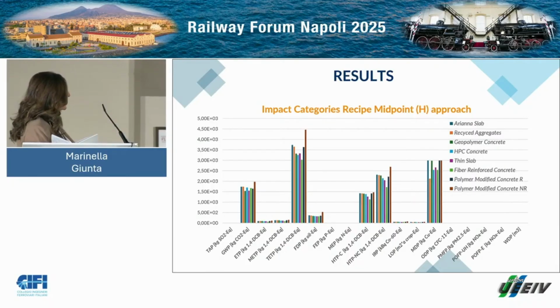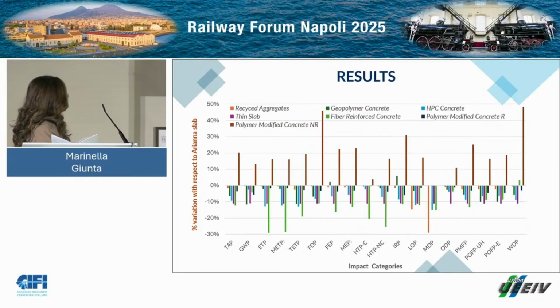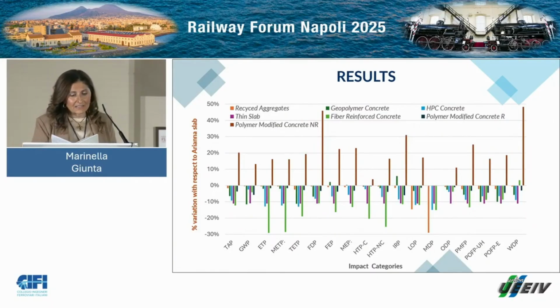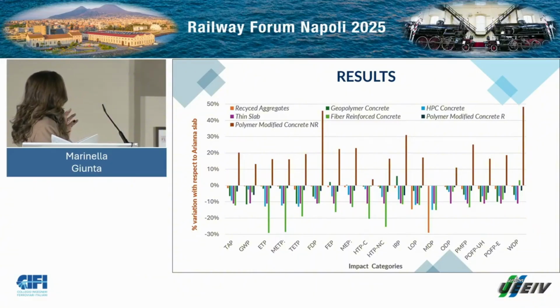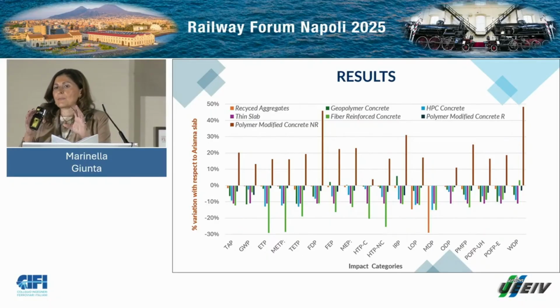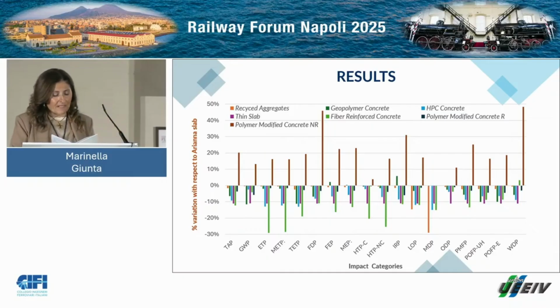Inside these impact categories, it's possible to observe different performance of the alternatives. For example, the polymer modified concrete with virgin polymer presents the highest values, while the fiber reinforced concrete the lowest. To analyze these results better, in this graph is reported the percentage variation with respect to the Arianna slab, the reference scenario. Positive values indicate a worsening, while negative values represent an improvement with respect to the reference scenario.